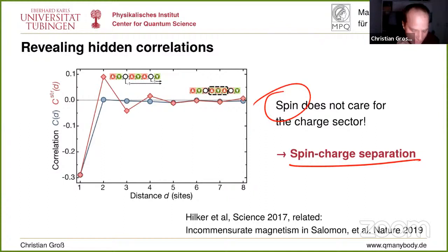So to really simulate real materials, I think what we need is a bit more programmability of the system, because what we have here, I call that the Fermi-Hubbard model, but it is the simplest Fermi-Hubbard model that you can have. On-site interaction, nearest neighbor hopping. That doesn't really model a real material. For real material modeling, you need a few more parameters. You need next-nearest neighbor hopping. You need maybe a nearest neighbor interaction, things like this, right? So this bit of programmability, maybe unit cell engineering in some sense. I mean, this we do already, but more complex unit cell engineering. And I think then we are not that far away from actually giving useful insight also for models for materials, right? I'm really strict with this: models for materials, because if you say you really model a material one-to-one, that's quite a future dream at the moment.